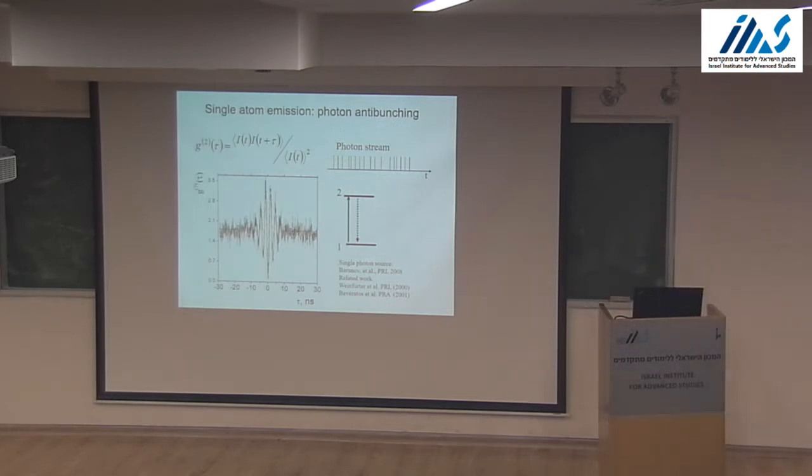First of all, about optical transitions. What I show here is the g2 function of light emitted by this single defect. If you collect the light from every single dot in this implantation pattern, you see that the light exhibits a non-classical character in the sense of anti-bunching: at zero delay time, photons emitted by a single atom are always separated.